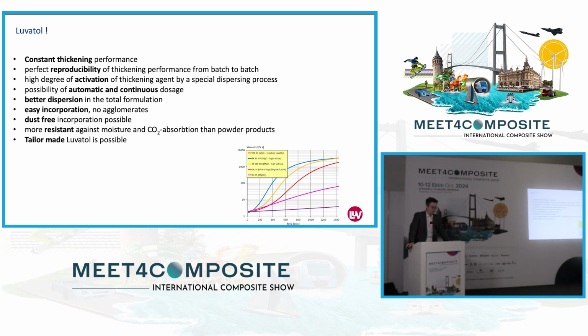What do you get out of the Luvatol is then, if you use it instead of, for example, a powder, you get a constant thickening performance, which is always the same. If we have here people who are using MGO powder in SMC and BMC, you well know that even from batch to batch, you have to be careful here, to insert more or less material and to adjust during your production. So it's always like a handling up and down. And that's different with the Luvatol. This handling and setting of the materials is done by us then.